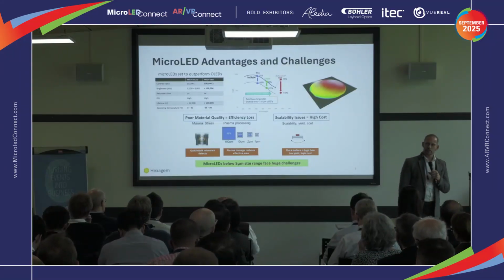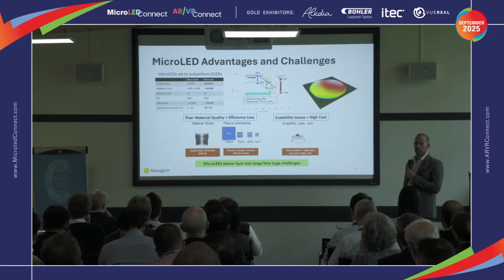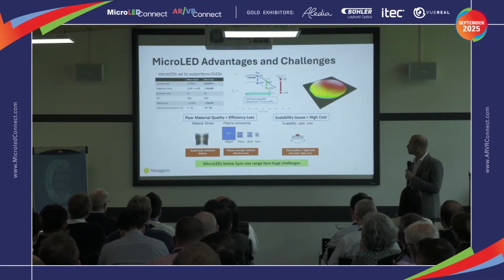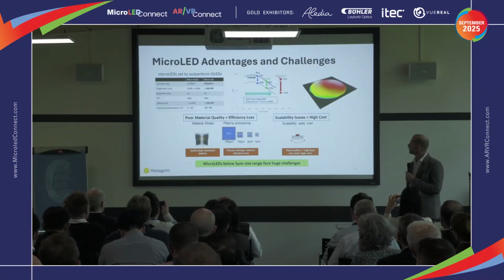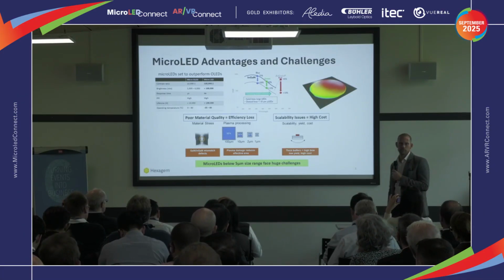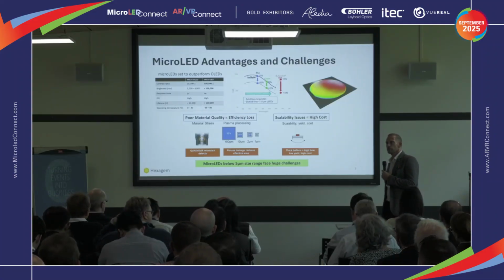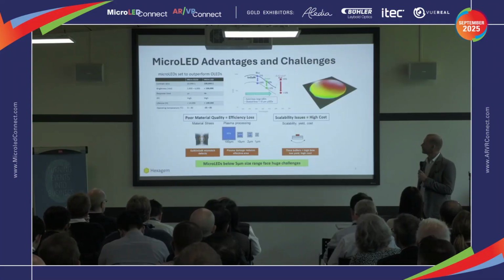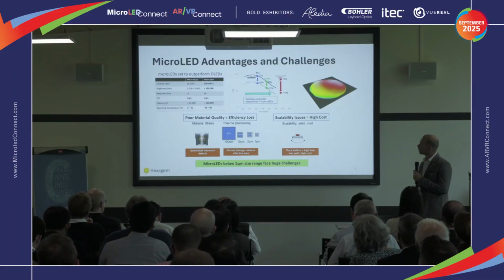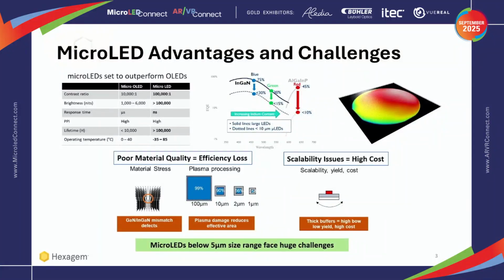All right, so microLEDs have a lot of potential advantages: ultra high brightness, high contrast, fast switching, stable materials, long lifetimes, higher operating temperatures than OLEDs, for instance. Of course, these advantages also come with challenges, and the two we are mainly focused on with our technology are the loss of efficiency as you scale down the LEDs, in particular below 10 microns or so. It's typically the case for all colors. Red is the most difficult one. And then the issue of wafer bow when you go to large wafers.